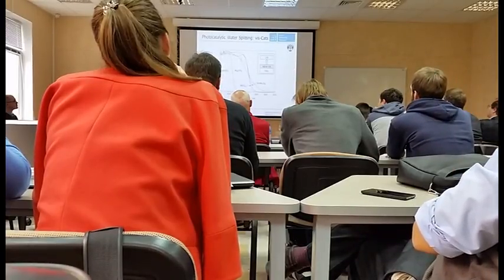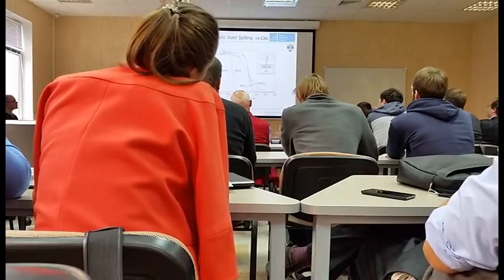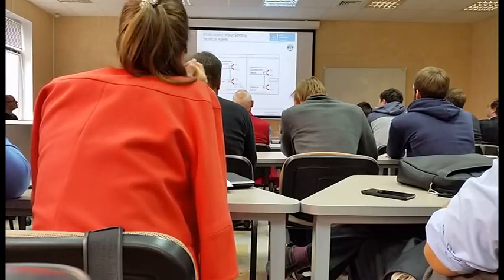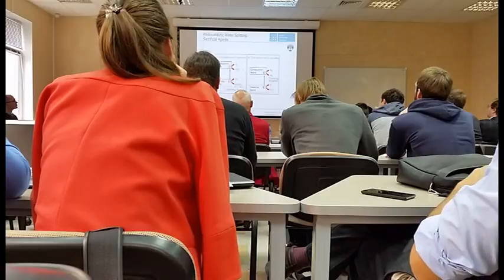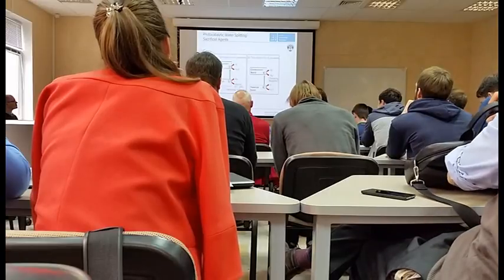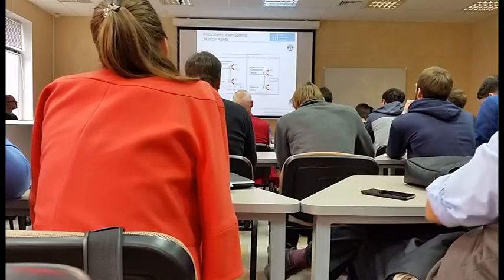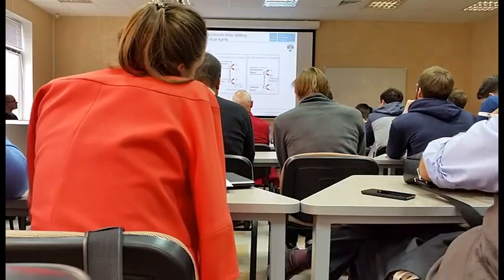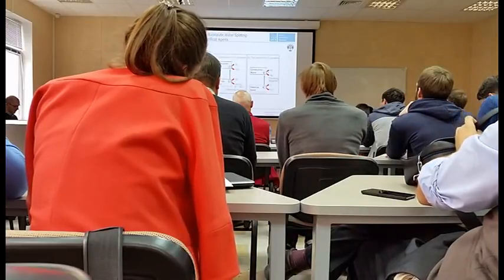For visible light applications, people have been able to shift the absorbance into the visible, but in most cases, and I will talk a little more about this in a minute or two, people have just taken so-called sacrificial systems. They looked only at the reduction of water, and they didn't oxidize water, but oxidized, for example, sulfide to sulfate or sulfite to sulfate. And when they were looking at the oxygen formation, they once again used sacrificial systems, and the most popular one is reducing silver to silver metal.